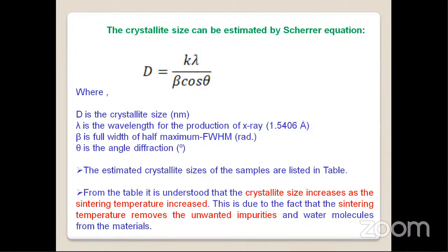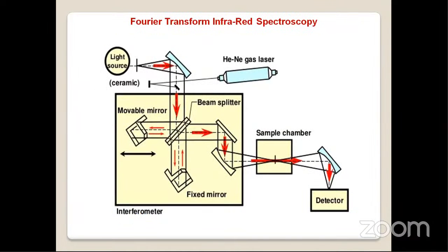This is the formula which I used for the calculation of crystallite size. It is in the nanometer range. Lambda is the wavelength of the X-ray we are using, beta is the full width at half maximum value, and theta is the angle in degrees. All these estimated crystallite sizes have been presented in the previous table. From the table, it is understood that, as we discussed, the crystallite size increases as the sintering temperature increases. The sintering temperature also removes unwanted impurities and water molecules. At the same time, the growing of grains results in the increment of crystallite size. Then the next study is Fourier transform infrared spectroscopy.